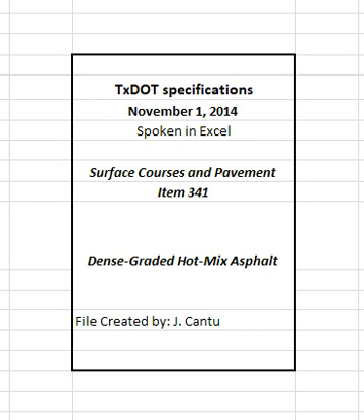2.7.1 RAP. RAP is salvaged, milled, pulverized, broken, or crushed asphalt pavement. Crush or break RAP so that 100% of the particles pass the 2 inch sieve. Fractionated RAP is defined as two or more RAP stockpiles, divided into coarse and fine fractions. Use of contractor-owned RAP including HMA plant waste is permitted unless otherwise shown on the plans.